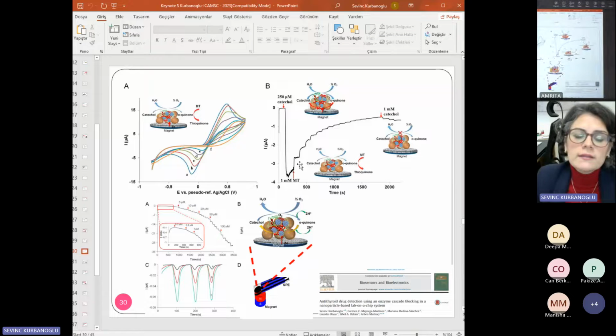In this case, the inhibitor, the drug, and the catechol are in the same measurement cell. So in the end of injections, with different concentrations of drug, when we add 1 millimolar, a very high concentration, 4 times higher than the initial one, you may see very little response. It means that during this 1000 second time, tyrosinase is also inhibited by the drug. And when we add catechol, its response is also connected to the drug, and we can see both inhibition types of this drug.